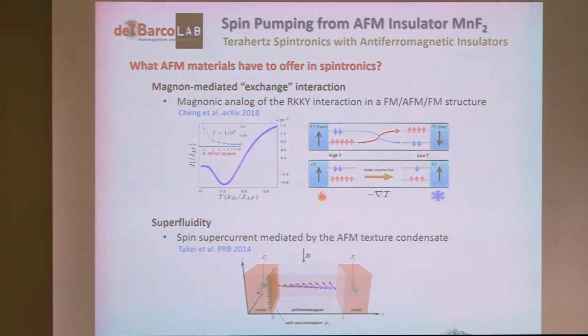All right, so from the physics point of view, there are also some other things that are of very high interest, at least for our team. One of them is, well, actually you can realize a coupling between two ferromagnets through an antiferromagnet that is mediated by magnons. So remember, we're talking about an antiferromagnet that is an insulator. So the exchange interaction between two ferromagnets, the archaic way that you would get in two ferromagnets separated by a metallic spacer, wouldn't be possible in this case.